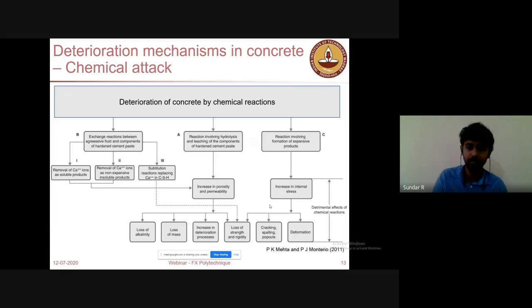So mainly if you see the corrosion issues, like this here, the expansive products refer to the expansive products based on corrosion and sulfate attack. And increase in permeability and porosity is primarily due to the leaching of compounds from the concrete. So when water passes inside the concrete, and it removes the calcium ions from the concrete matrix, then it will eventually reduce the serviceability of the concrete by letting further entry of ions into it.